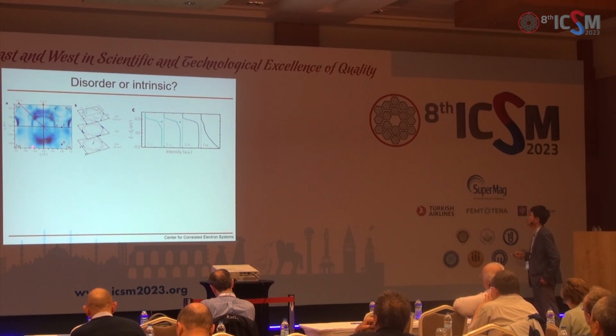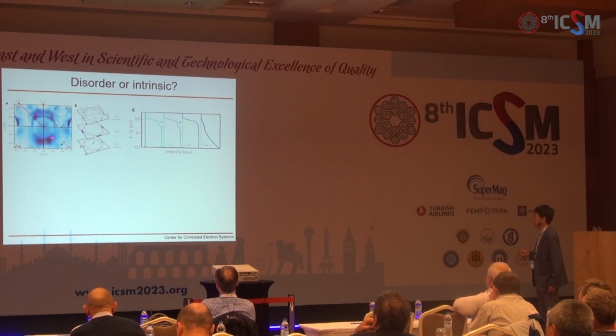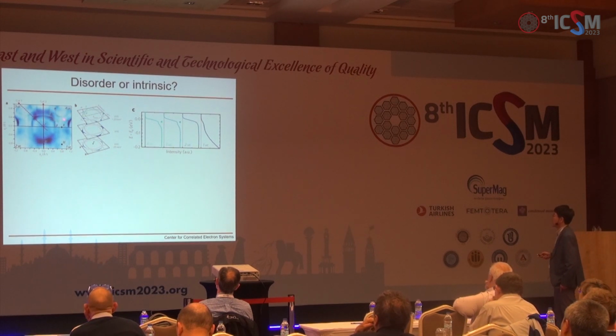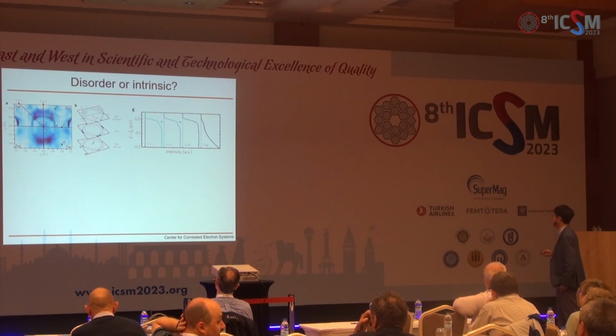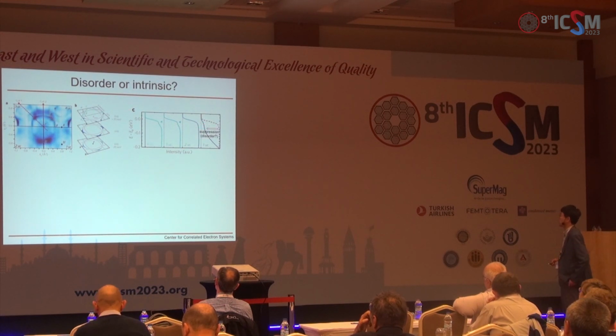Here I'm plotting 1, 2, 3, 4, 5 unit cell Fermi surfaces. For one unit cell, we have clear Fermi surfaces. Here it's a little blurred, but we still have fairly some spectral weight even down to 1 unit cell. Now, if I compare the thickness-dependent Fermi edge here, 4, 3, 2, 1, you see that even though we still have a metallic edge compared to 4 unit cell, the spectral weight is fairly suppressed.